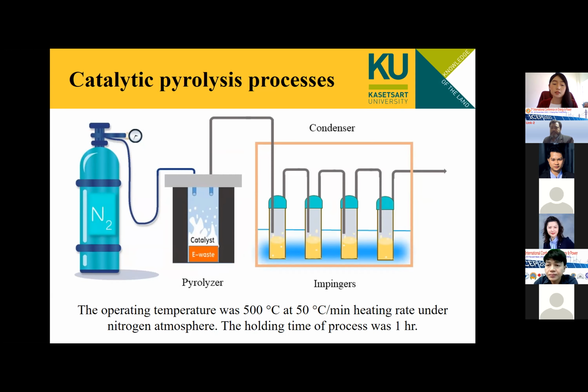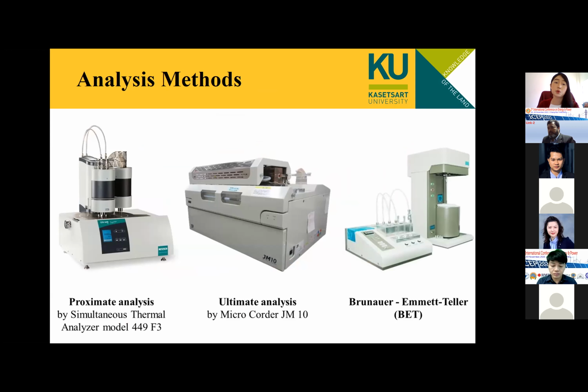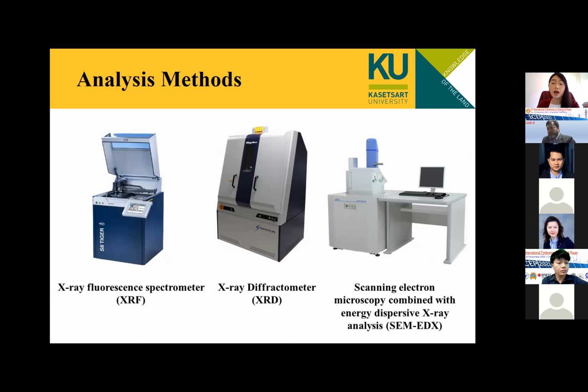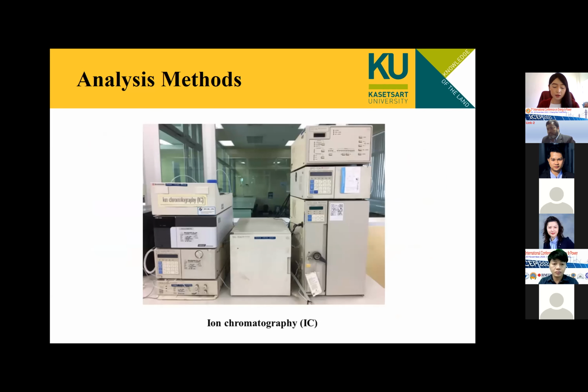Catalytic pyrolysis process. The input of these experiments consists of 50 grams of the raw material and 10 grams of the catalyst. The operating temperature was 500 Celsius with a heating rate of 50 Celsius per minute under a nitrogen atmosphere. The holding time of the process was 1 hour. This picture shows the analysis methods: proximate analysis, ultimate analysis, TGA, XRF, XRD, SEM, EDX, and the last one is ion chromatography (IC).